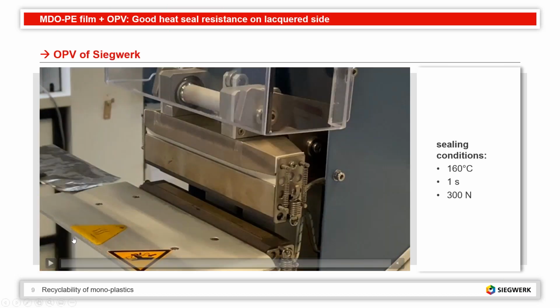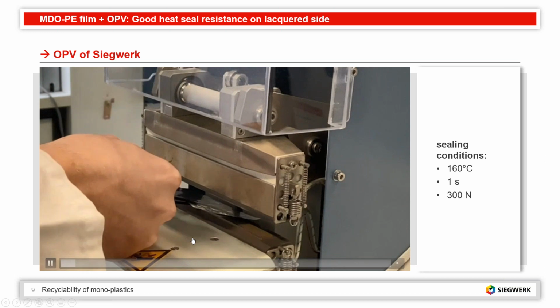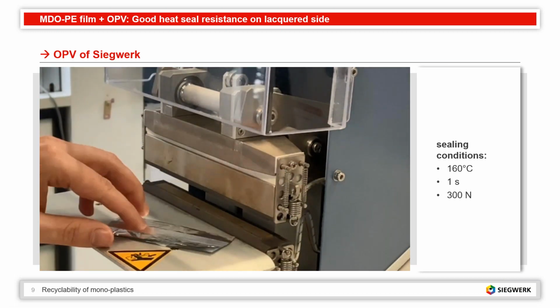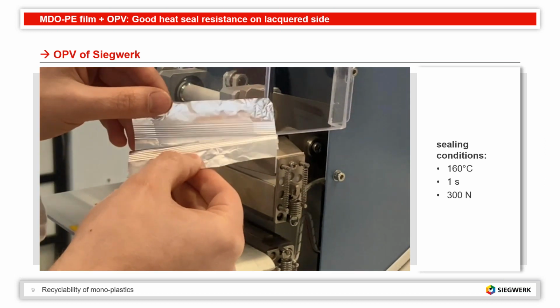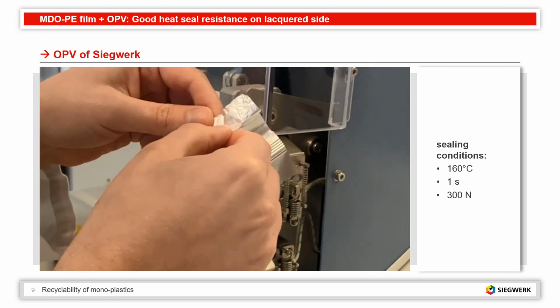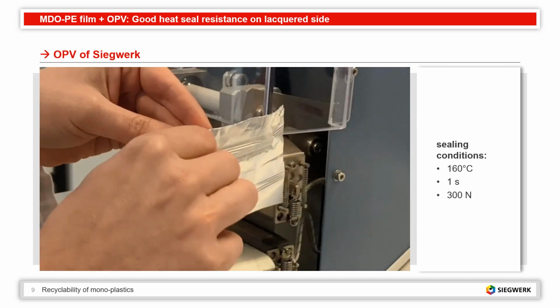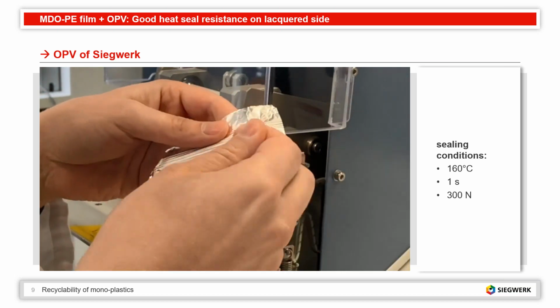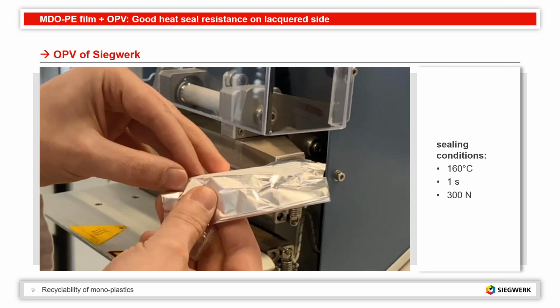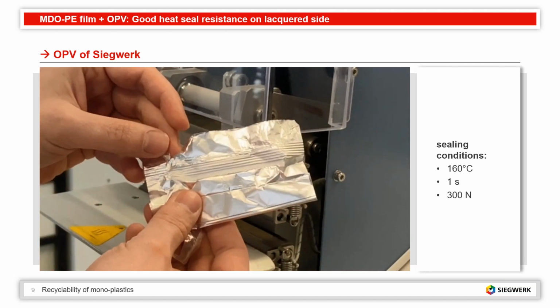Now, what we've done next is we have covered one side of this MDO-PE film with our OPV, our special heat seal resistant OPV. And we repeat the same process, again 160 degrees for 1 second and 300 Newton. And you see that he can now easily open the aluminum again, but when he tries to remove the strip from the other side, it's glued, it sticks to the aluminum, it tears, he can't remove it. And this is because the side that was covered with our heat seal lacquer did not adhere to the aluminum, but the unprotected side, of course, is still gluing to the aluminum under these conditions. So you see, we can make a big difference in the machinability of such a structure just by applying this heat seal lacquer, for instance.